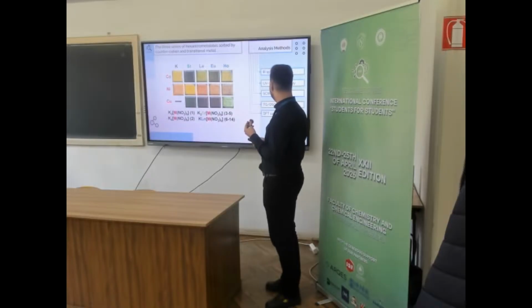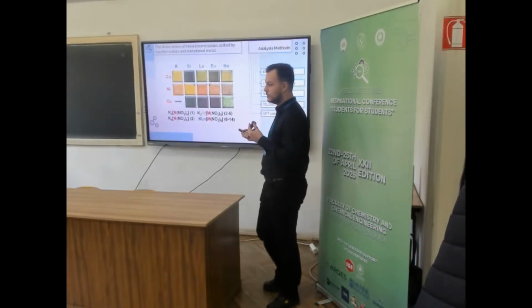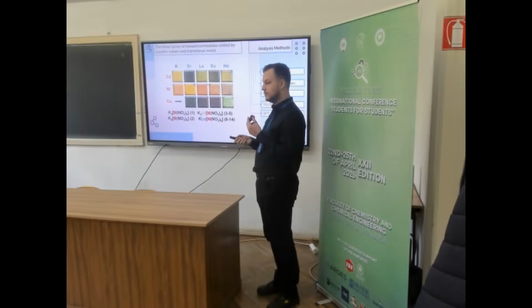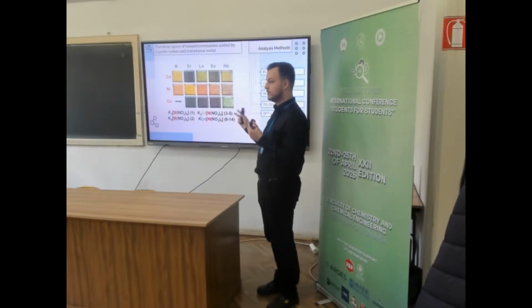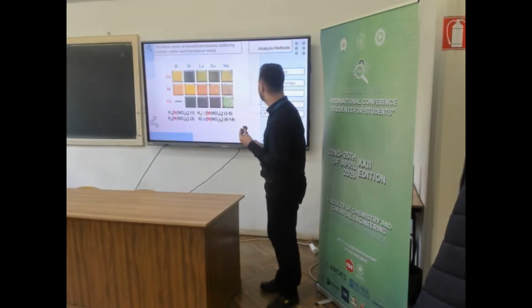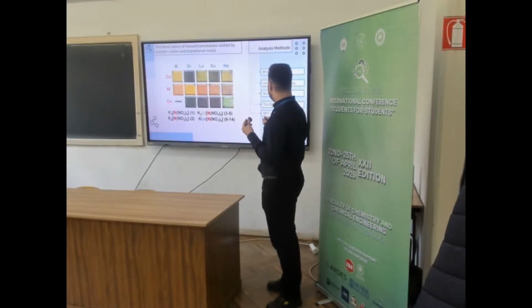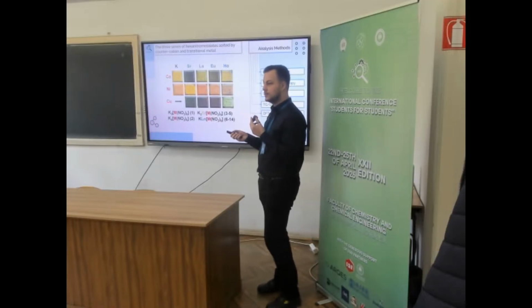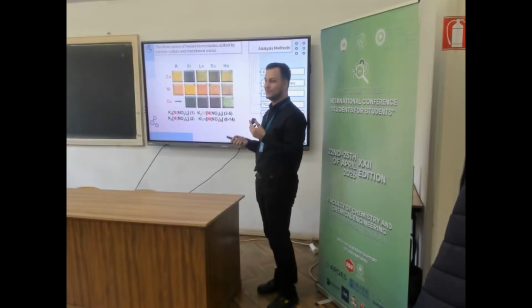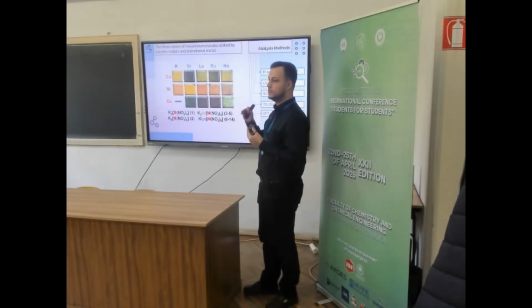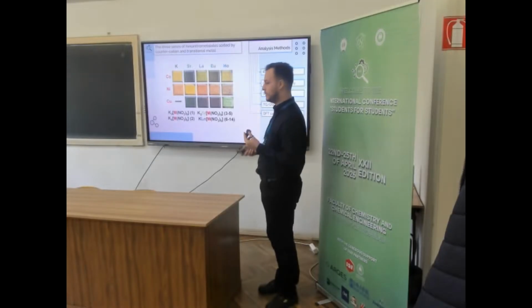Furthermore, the powder X-ray diffraction was done on the complexes, and we observed that those with two different counter ions were isostructural, of course, with small differences. And the single crystal X-ray diffraction, we managed to grow just one crystal, unfortunately, but the structure that was unraveled was used as a base for our DFT calculations in order to better understand the IR spectrum.